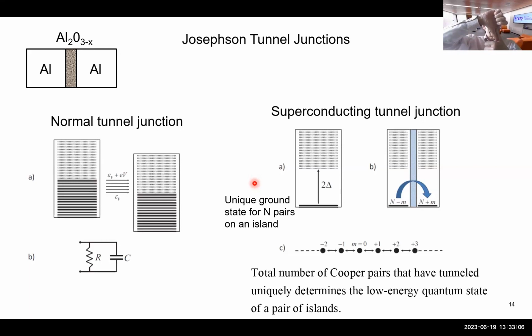Oh, well, 2 delta: the electrons are paired up with opposite spins, and very crudely speaking it's now a spinless boson, and they all Bose condense. That's not strictly right, but it's basically right. And the 2 delta is the energy cost to break apart these pairs into 2 quasi-particles, one spin up and one spin down, that can now travel separately. Their binding energy is 2 delta, and the scale of it is the same as the critical temperature of the superconductor, a few Kelvin. And of course, it's very useful to know that 1 Kelvin corresponds to Planck's constant times 21 gigahertz in frequency units. So the gap in aluminum is 100 gigahertz or something.